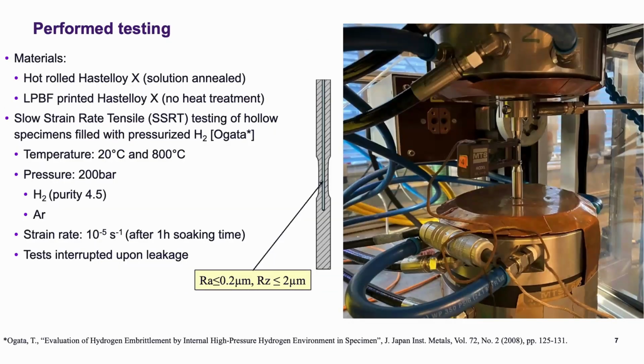Okay, the whole specimen testing method has already been introduced several times, I think. And as I mentioned, we are testing two different materials, the hot rolled Hastelloy X, which is also in a solution anneal condition, which I perhaps didn't mention, whereas the additively manufactured material is used in the as printed condition. So we do slow strain rate tensile testing at the temperature of 20 degrees and 800 degrees. And we have an internal pressure of 200 bars and a strain rate of 10 to the -5.